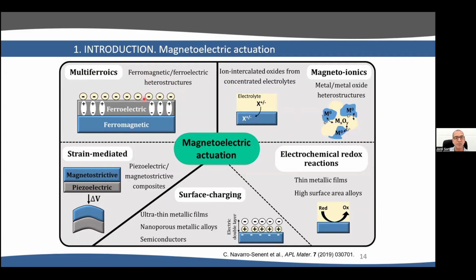We can start with what I was commenting on, these multiferroic materials, in which ferroelectric and ferromagnetic orders are mutually coupled, and they can be single-phase materials or heterostructures. Single-phase materials are scarce, especially showing multiferroic properties at room temperature. That is why heterostructures are commonly fabricated. Here, when you apply voltage, the ferroelectric material, which is also piezo, deforms, and this deformation is then transferred through the interface to the magnetostrictive material, changing its properties. But of course, this has a problem of fatigue. If you deform the material many times, in the end it breaks.